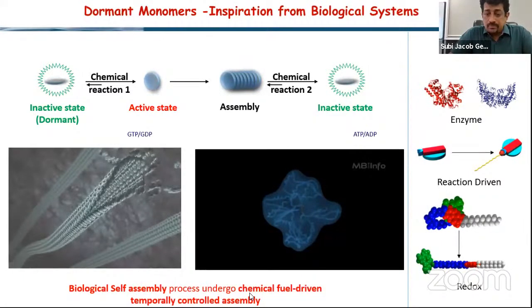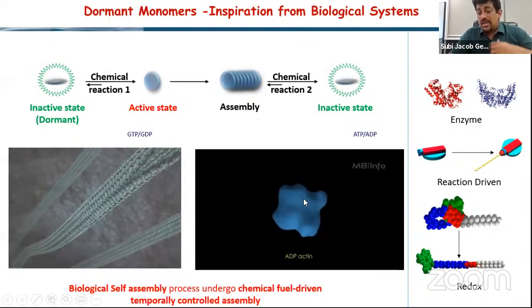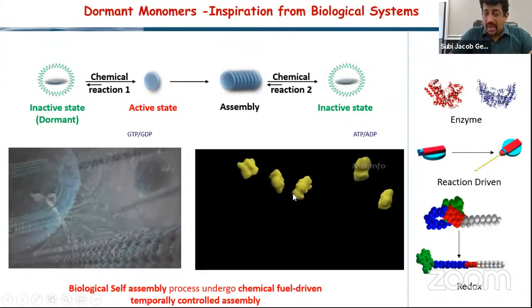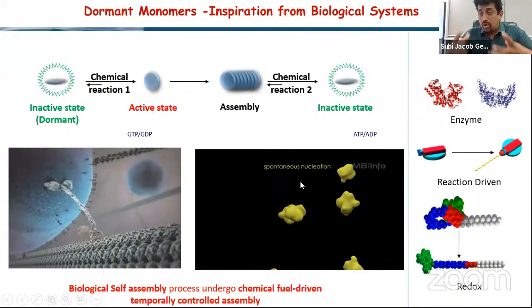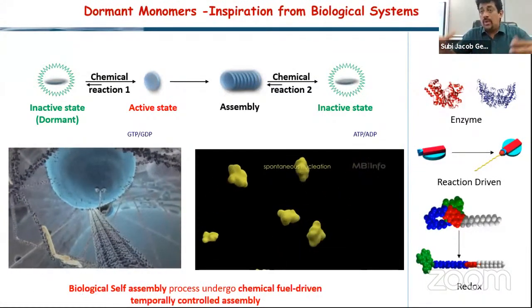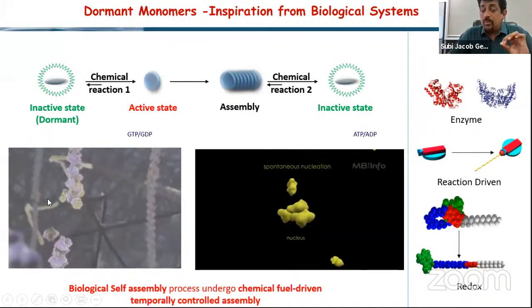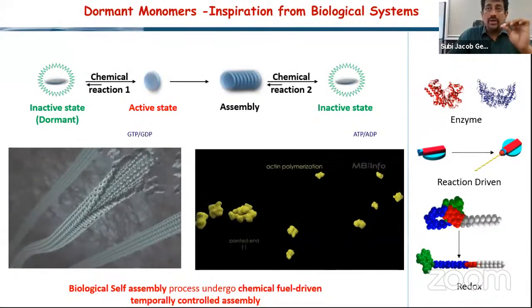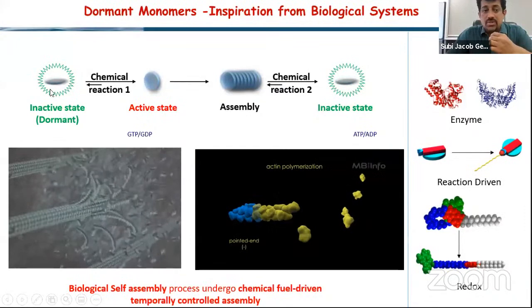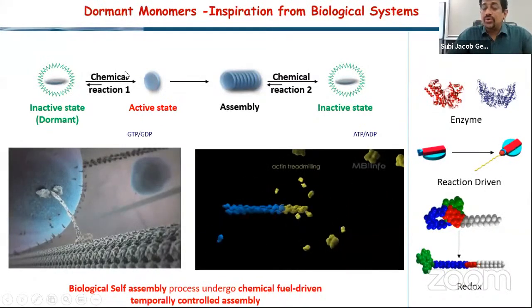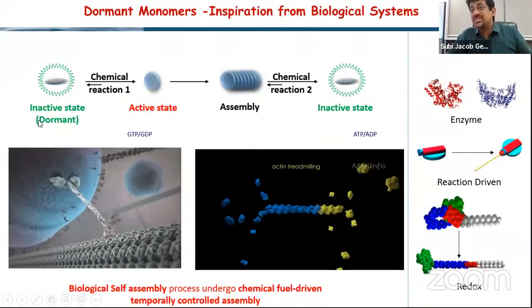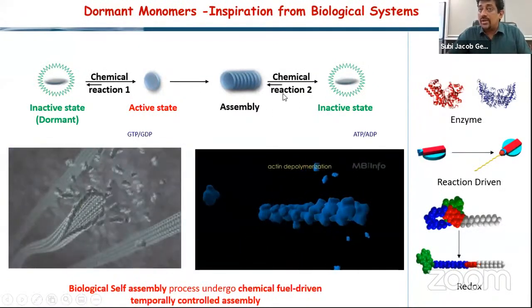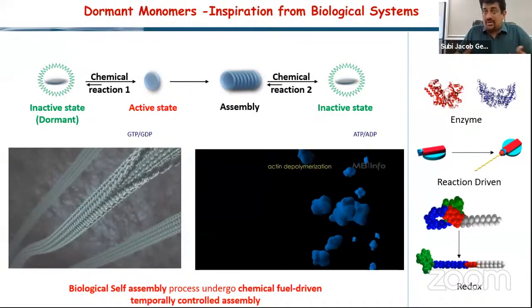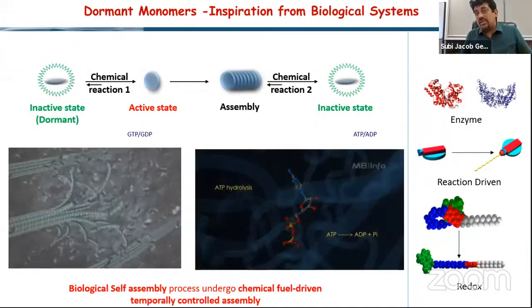We came up with something called fuel-driven assemblies, because we looked into biological systems and found that there is a dormant state. If you take actin polymerization, there is an actin monomer which is in a kind of dormant state. It will not grow until it is triggered by ATP binding. Similarly in microtubules, the tubulin monomers will not grow unless triggered by GTP. So it is called a fuel-driven assembly. The monomer remains in a dormant state. You trigger it with a chemical reaction, then there is a conformational change in the monomeric system, it goes from an inactive state to an active state, and it grows. Then there is another chemical reaction which hydrolyzes this energy carrier, ATP or GTP, to ADP and Pi, bringing the materials back to equilibrium.